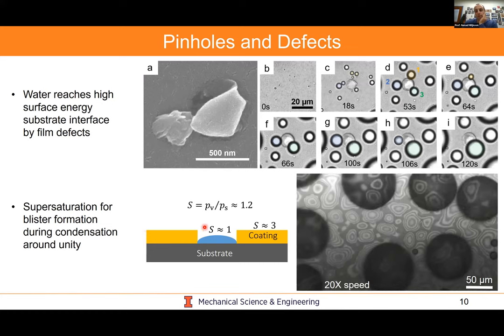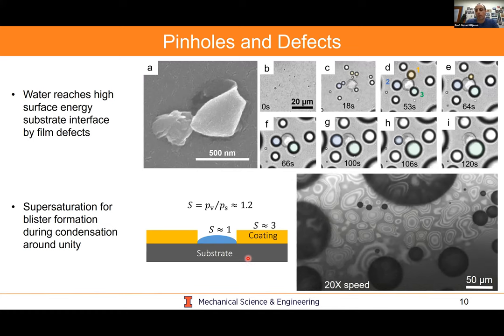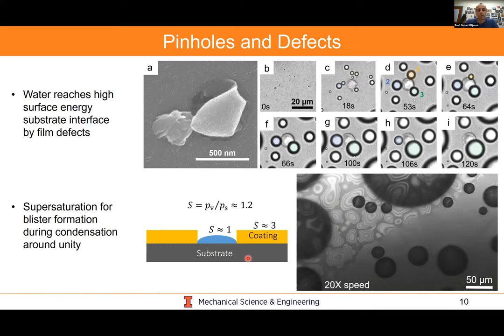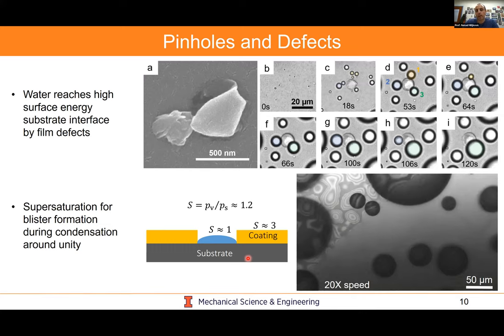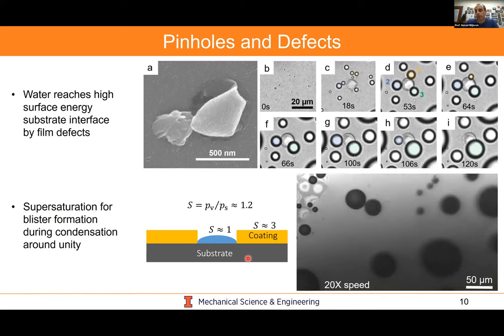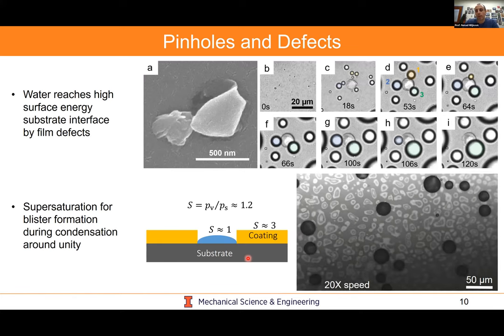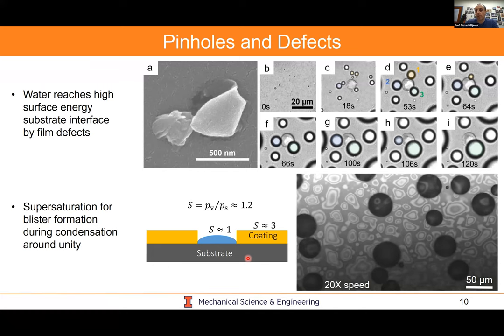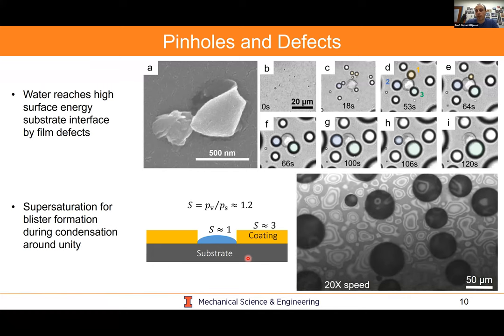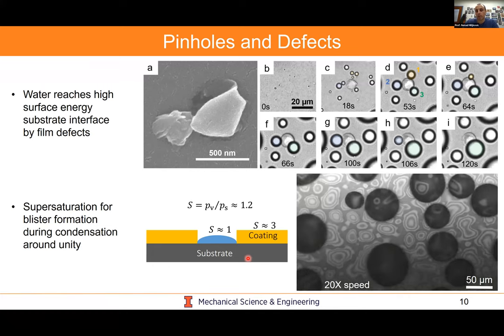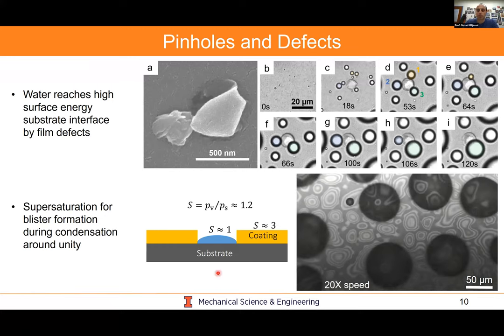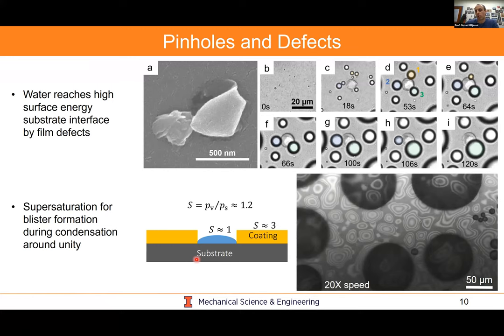And this is actually also in agreement with previous studies looking at condensation on hydrophobic substrates, where the critical supersaturation for condensation typically is on the order of 2 to 3. But experimentally, what experimentalists always show is that typically whenever you condense on a hydrophobic coating, you will see condensation very early on at very low supersaturations, as if the coating was hydrophilic. And this makes complete sense because if you expose a substrate, you expose OH groups, you have a high surface energy, and the coating itself will behave as a hydrophilic coating.